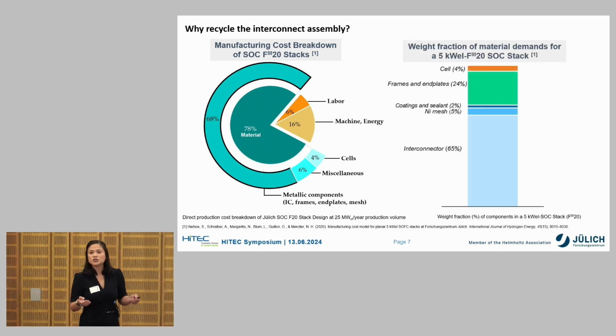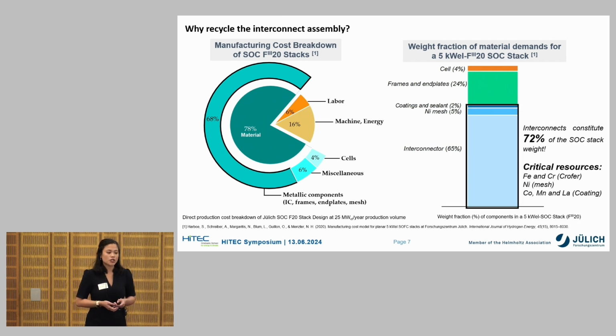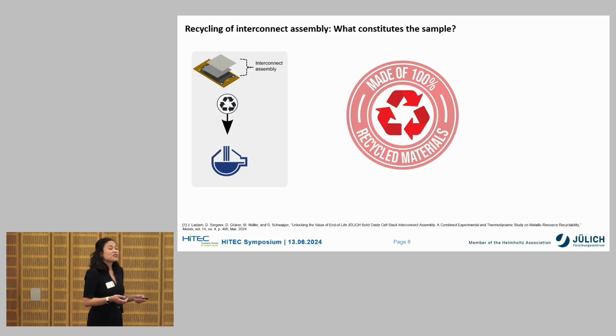Furthermore, interconnects also dominate the stack in terms of net materials demands, taking 72% of the total stack weight and containing critical resources in the form of iron and chromium from the Crofer, nickel from the mesh, and cobalt, manganese, and lanthanum from the coating layers. The good thing about these parts is that they are steel-based, and steel is in principle infinitely recyclable.